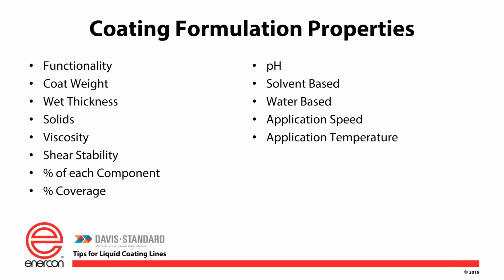All right, we need to know if we're going to be heating these coatings, if the rolls in the coaters need to be heated, your coating supply systems, whether or not they're heated or cooled. And in a lot of cases, the coater will be temperature controlled. It won't really be heated. We're going to put around an 80-degree Fahrenheit water through it because the shear that's created within your application method will actually make rolls swell. They're made out of steel. They will swell, become larger. And we want these to maintain constant all day long. So if you put a known temperature through and control the roll to a set temperature, your process is constant all day long. However, some coatings do need to be heated.